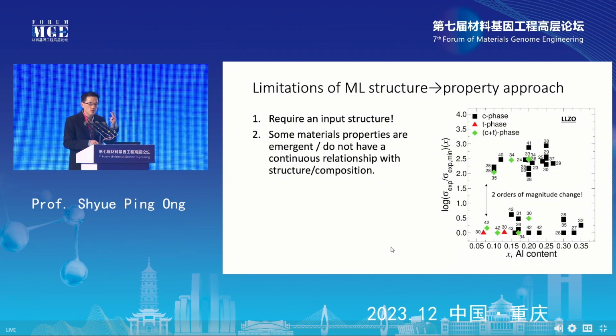You can get a 2 orders of magnitude increase or decrease in the ionic conductivity just with a little bit of aluminum or with a phase change from the tetragonal phase to the cubic phase, right? And this kind of 2 orders of magnitude change, or very discontinuous change, is very, very hard for machine learning models to model properly, okay?